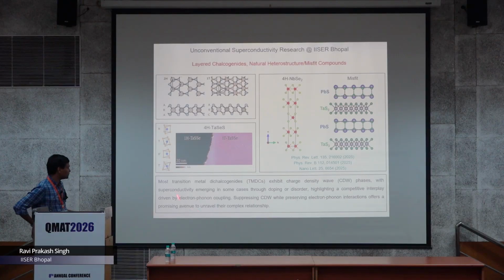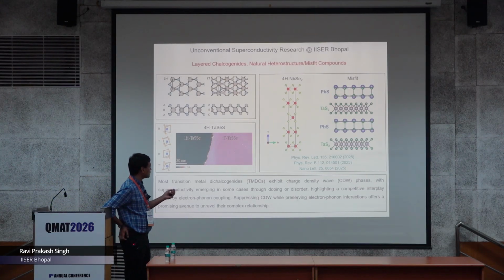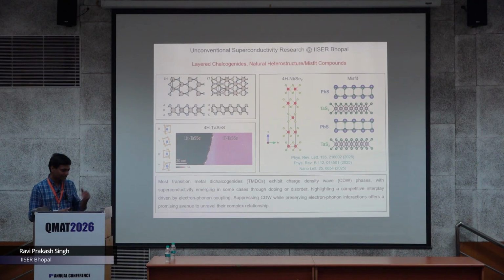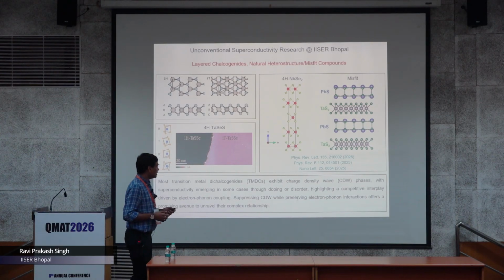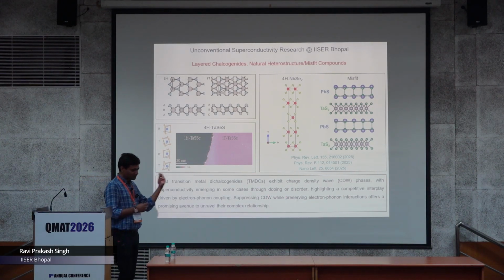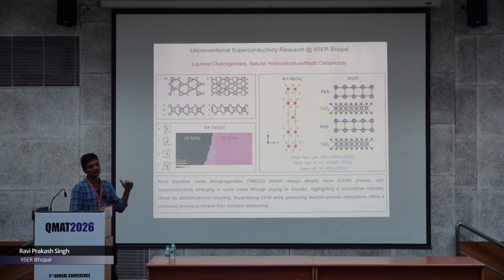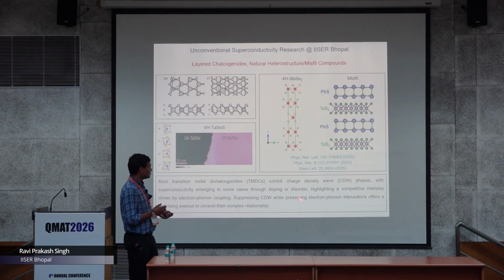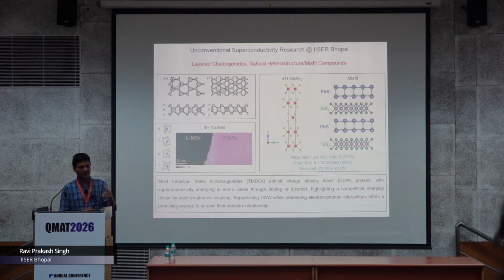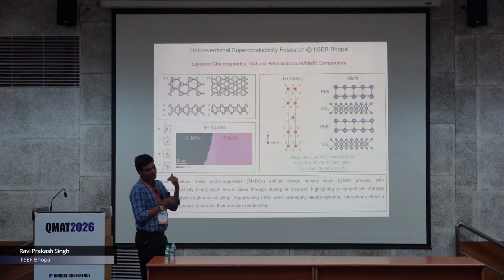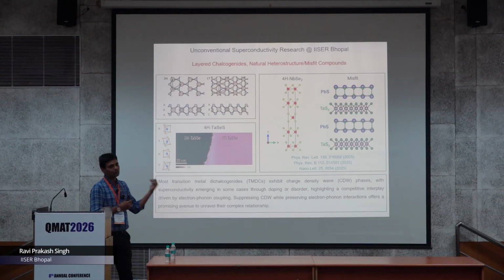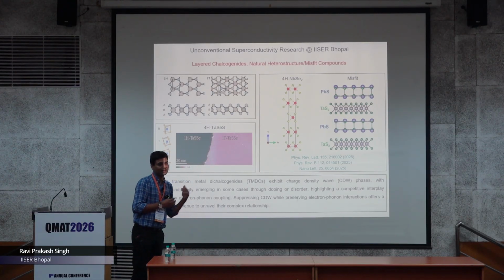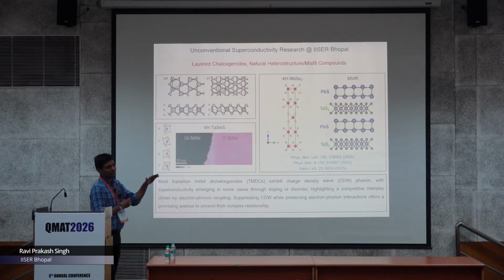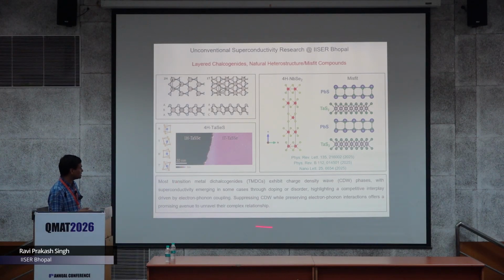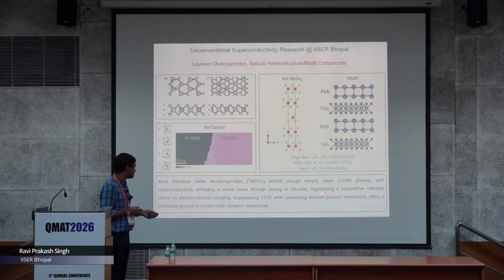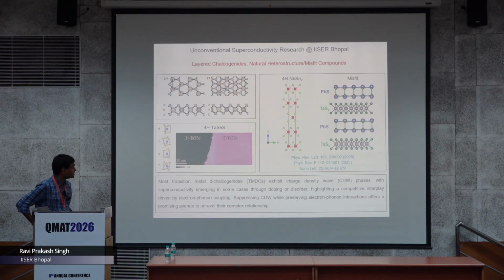And the reason for working on these metal chalcogenides is that they have very high spin orbital coupling, but not many are superconductors, or they are superconducting at very low temperature. But most of them have charge density wave, and by suppressing it in many cases we are able to induce the superconductivity or enhance the superconducting transition from the millikelvin range to like 2 or 3 Kelvin. So that was one motivation for working on these chalcogenides.